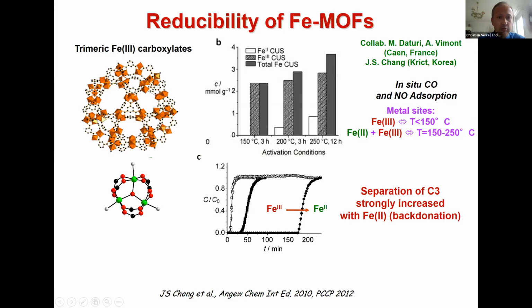On the trimer, you've got 2 water molecules initially, and 1 OH or fluorine group. When you dehydrate, these water molecules go first, and then when higher temperatures are reached, you can even remove this anion, and this allows the creation of an additional iron 2 metal site. It is very well known in the literature that these iron 2 open metal sites are good for back donation with unsaturated gas molecules, such as NO or olefins, for instance. So it creates an additional interaction that makes the interaction much stronger.